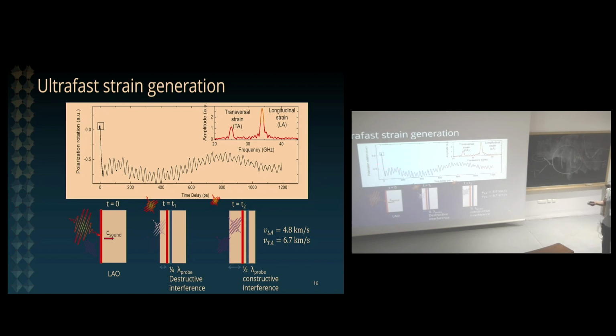You may remember from an electrodynamics course that associated with a resonance there is also a penetration depth. So there is an extinction of the electric field that is penetrating inside the surface of the material, typically a few hundreds of nanometers. So there is a strong asymmetric profile of electric field. Now there is decay inside the material when it's excited at resonance. These are electric fields of the order of tens of megavolt per centimeter. So the material inside this slab at the surface is undergoing an electrostrictive response, which will cause a lattice expansion.